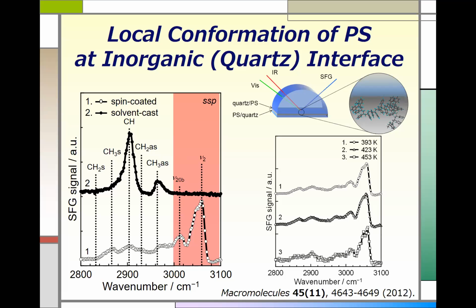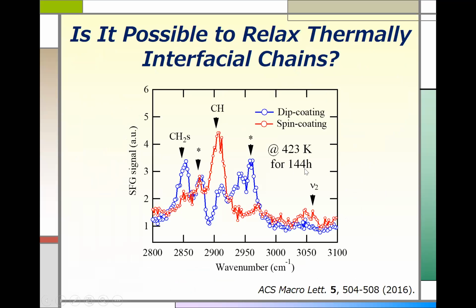But this peak, right, at 150 degrees Celsius, 423 Kelvin. And as I told you, this annealing time was 3 hours. But if we annealed longer, like 144 hours, that peak disappeared, or at least became smaller. Why is that? Because polymer chains could relax even at the solid substrate. So it's possible to relax polymer chains even at the solid substrate, but it's just slow and it takes time. That's what I'm talking about.